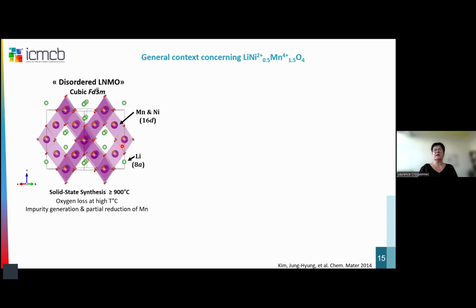But in fact, here I use this tilde because when we are doing these syntheses at high temperature, we always have a tendency to lose oxygen, and so not to have exactly this formula, but to have oxygen loss, reorganization of the material with generation of impurity, and then for charge compensation, reduction of manganese.